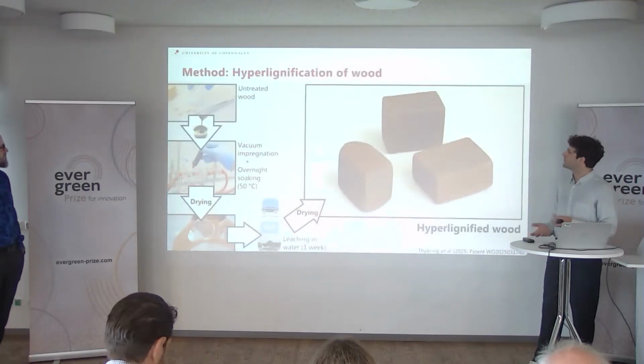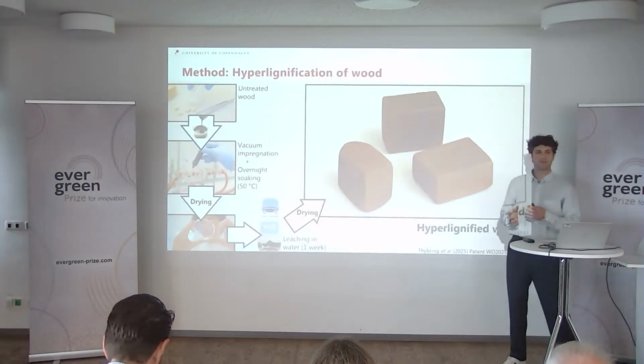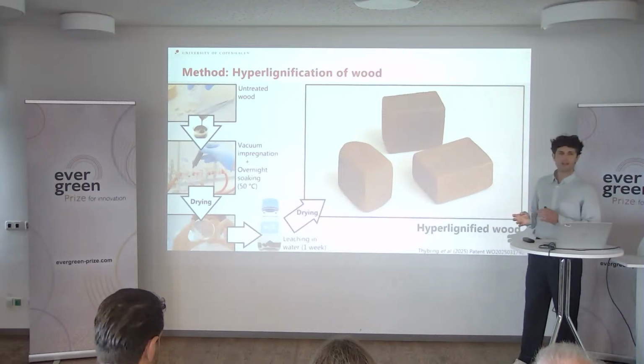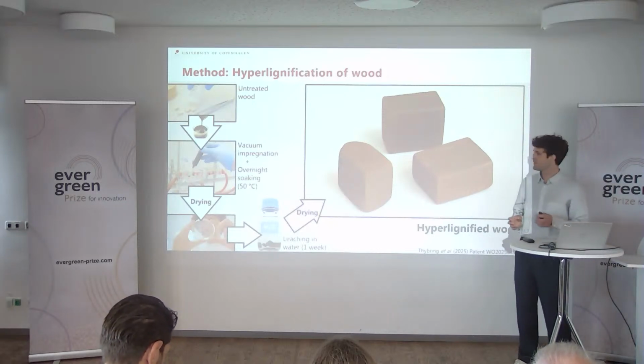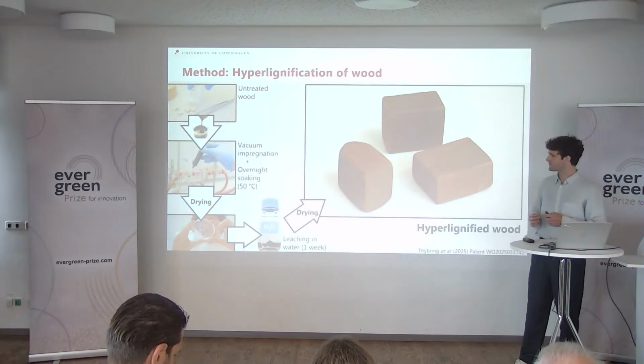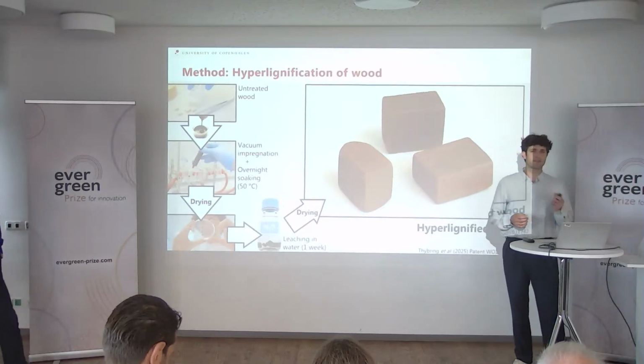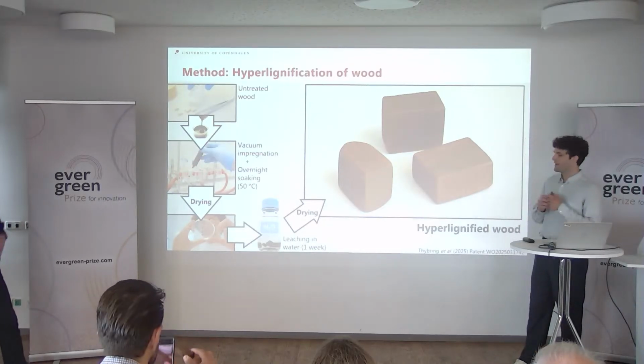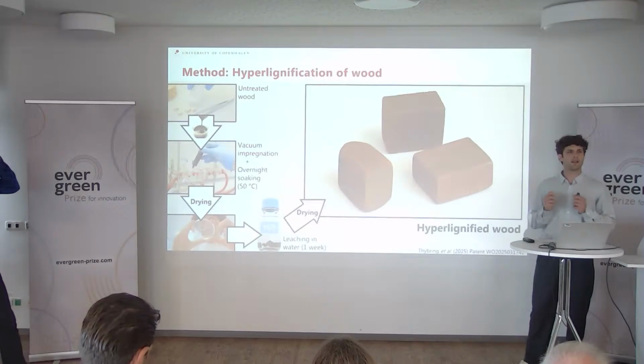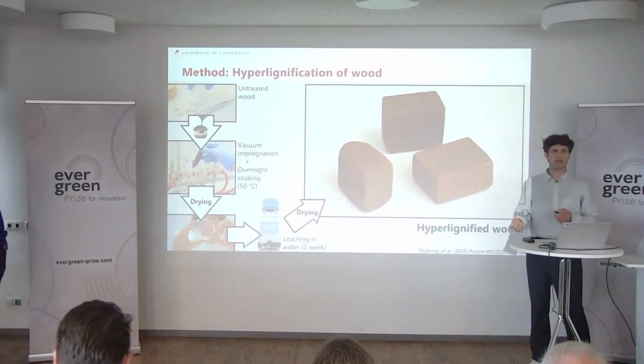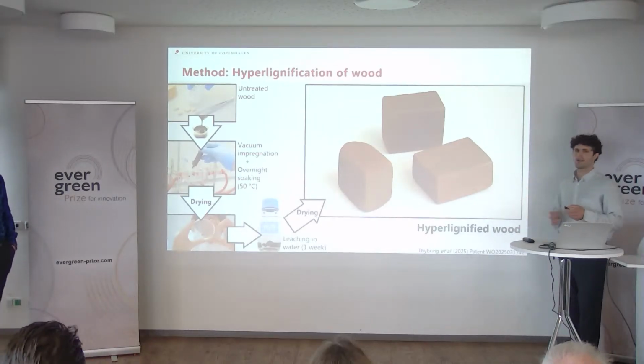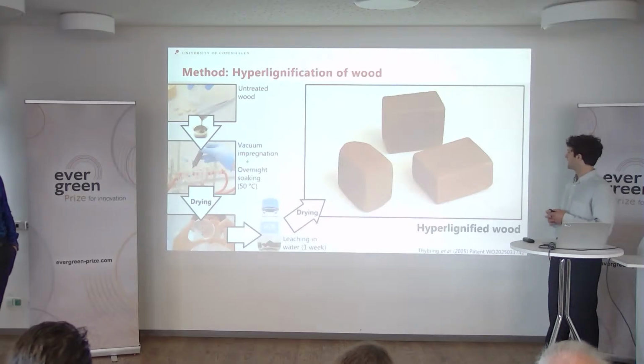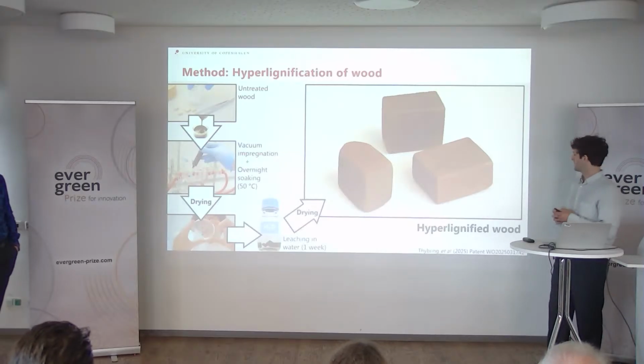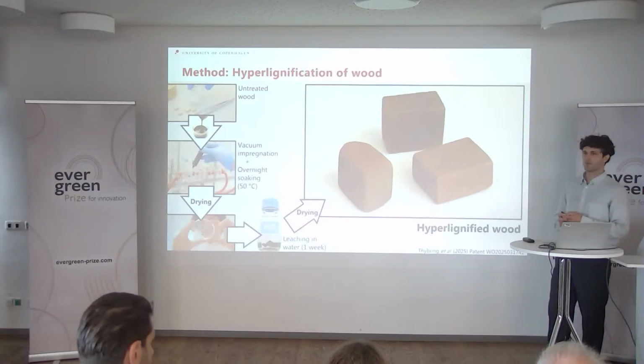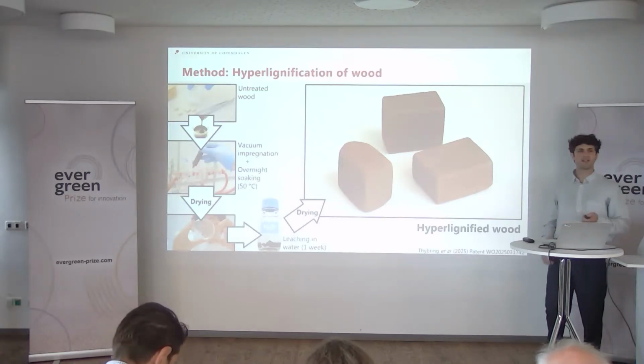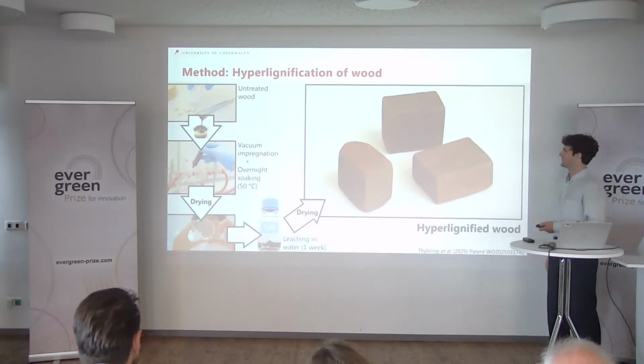But how did we do it? It was quite straightforward and simple because we used vacuum impregnation. Then we released the vacuum, soaked overnight at 50 degrees, and then dried the samples. After drying, we leached for a week to simulate outdoor weathering, and then dried again. So this is what we got at the end, and it really felt like deep penetration, and we call this hyperlignified wood.